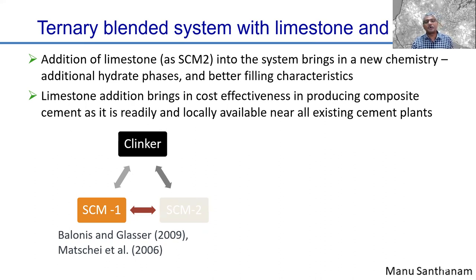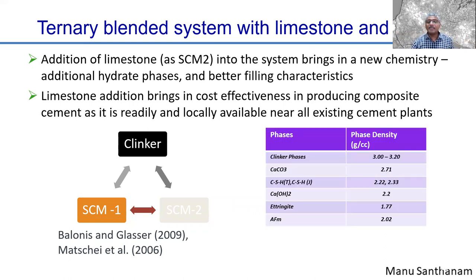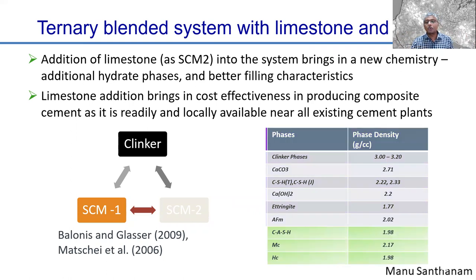What do you do here? First of all, you're reducing the cost because you're using limestone that is available already in the cement plants. You don't have to bring the supplementary material from a far off location. Secondly, you're converting these phases that form because of hydration of cement, which generally are slightly high density phases, into a mixture of low density phases. And these low density phases include, of course, more of ettringite.